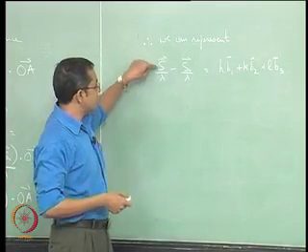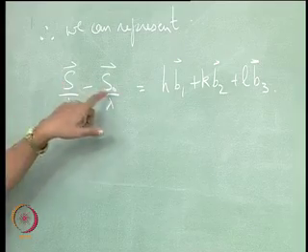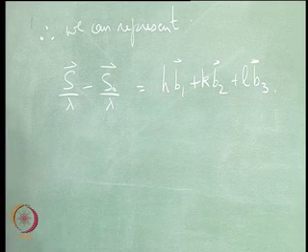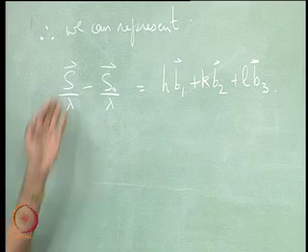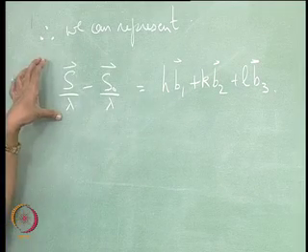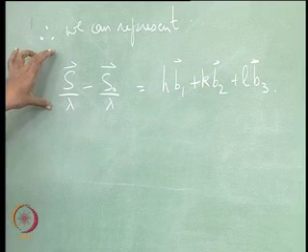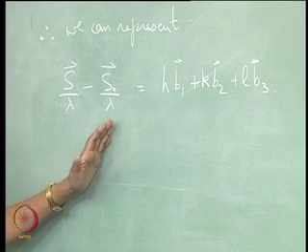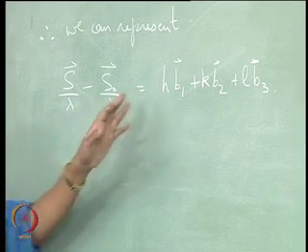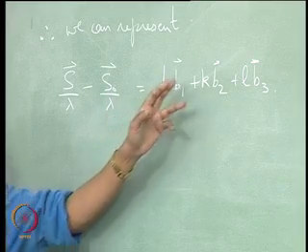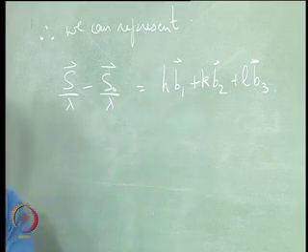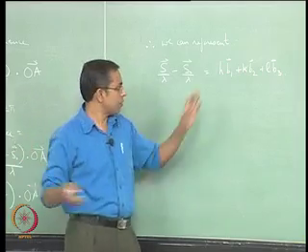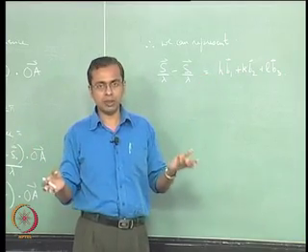So this S, this S0 and this lambda could have been anything. You have full freedom to select all of these three quantities, which is what the left hand side of this equation is. Since you have full freedom to select anything for the left hand side, it means that H, K and L can also be any arbitrary number. It could be an integer, it could be a fraction, one of them could be a fraction, anything could be true.